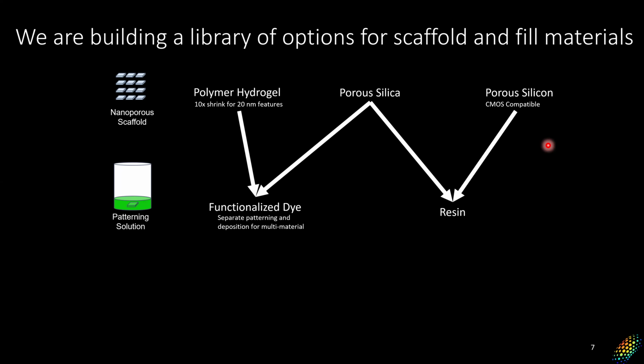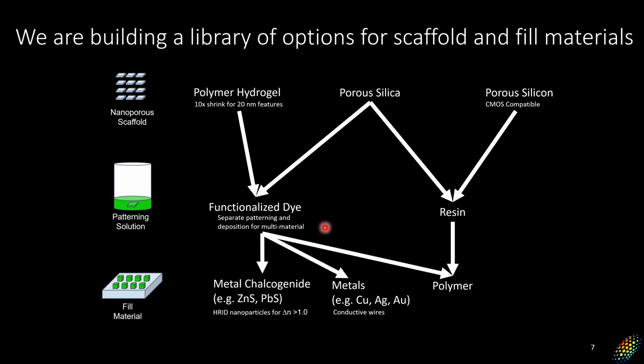And then in terms of fill materials, I mentioned resins, which give you polymers, but we also have a process where we can pattern functionalized dye molecules that have a specific chemical group that we can then attach a variety of materials to. So while resin just gives you polymer, with this dye, we've shown that we can grow metals. We've actually made conductive wires with a conductivity comparable to copper. And you can do other inorganic materials such as metal chalcogenides like zinc sulfide or lead sulfide, which lets you then get higher index contrast or expand out into other wave bands like the mid-wave or long-wave IR.